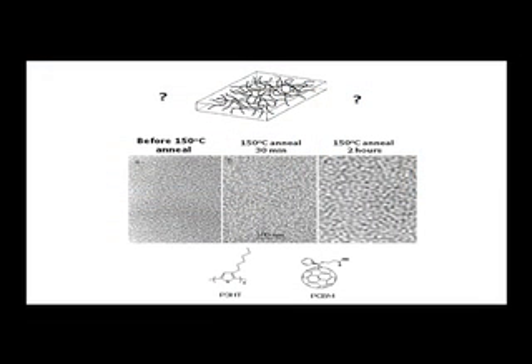In this particular case, what we've done is to use polythiophene, poly-3-hexylthiophene with the fullerene, more or less drawn to scale. This ring is comparable size here. And we've just mixed them, and we've cast a film of them. And when you do that, you get this structure. If you anneal, you get this structure.